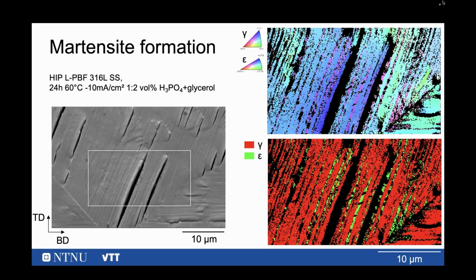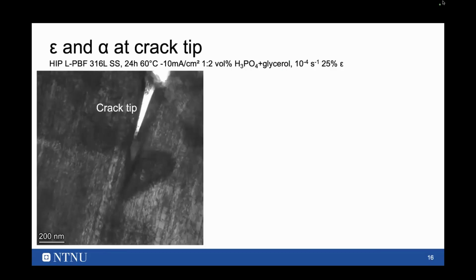I just want to remind you that this microstructure is quite close to the conventionally wrought microstructure, where we know there can also be martensite forming. We only saw epsilon martensite by this technique, but we went even further.